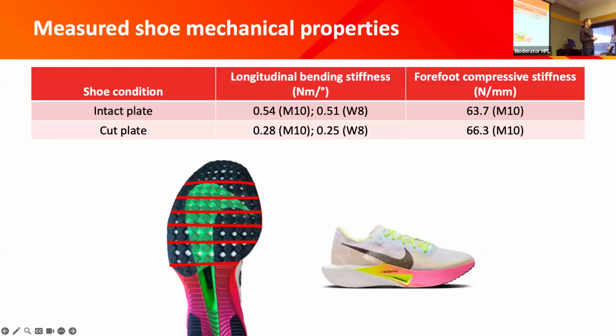All right, so some results. I wanted to make sure that the cuts that I made in the shoe were actually doing something. So I measured the longitudinal bending stiffness for the two shoe conditions. And I was also curious to see what that effect might have on just the compressive stiffness. So I just did some direct compressive measurements as well. So the intact plate condition for the men's and women's shoes is about 0.5 Newton meters per degree. And then the cut plate condition is about half that. So 0.28 and 0.25 for the men's and women's shoes respectively. So putting that carbon fiber plate in definitely had an effect in terms of longitudinal bending stiffness.